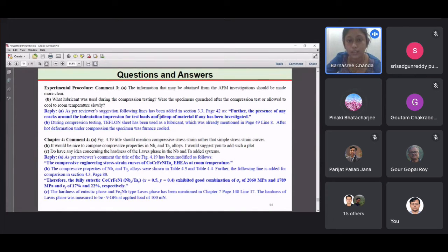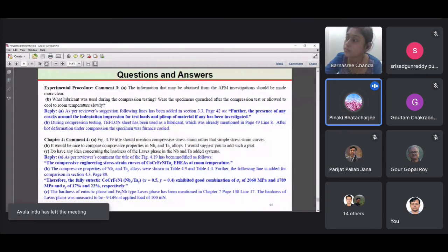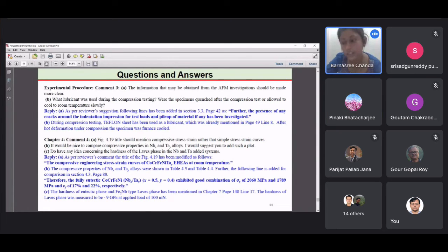And sir, for indentation, have you taken it in the FCC phase, or at the interface of the FCC and Laves? Sir, I have taken it on the Laves phase and on the matrix. Okay, so independently. Yes, sir, independently. Okay, so that means you get the mechanical properties behavior for the two independent phases, right? Yes, sir. One is for the eutectic matrix and one is for our Laves phase.